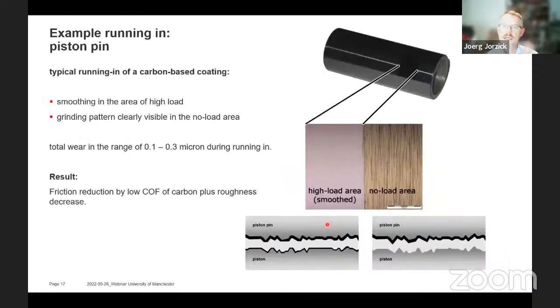And we looked a little bit into that for the application of piston pins. Here we have a piston pin that was coated with a DLC coating. It was put into an engine, and after 400 hours, we took out the piston pin and had a look at this area. So we saw areas that appeared more shiny and others that appeared more dull. If you look under the microscope, you see different areas, one where the load was applied and where this running in has happened, and you have a rather smooth area here, and the other area, the more dull area, where the load was not applied and where the coating as deposited.